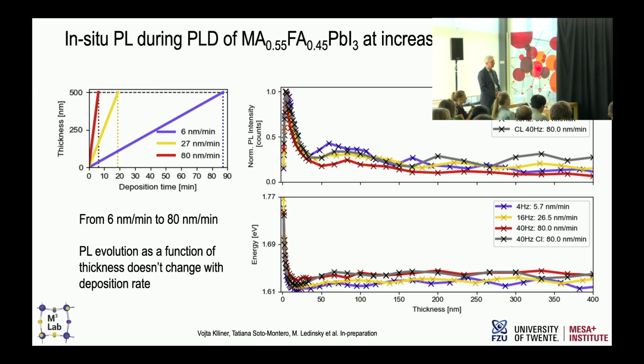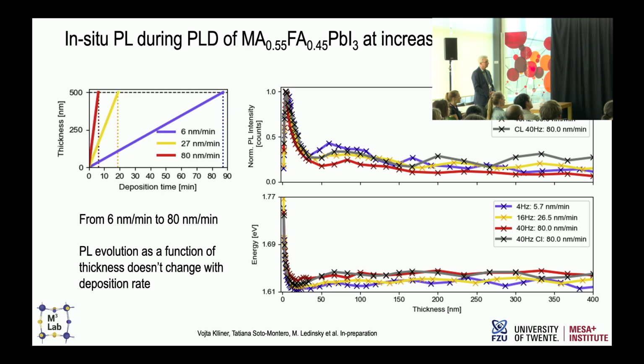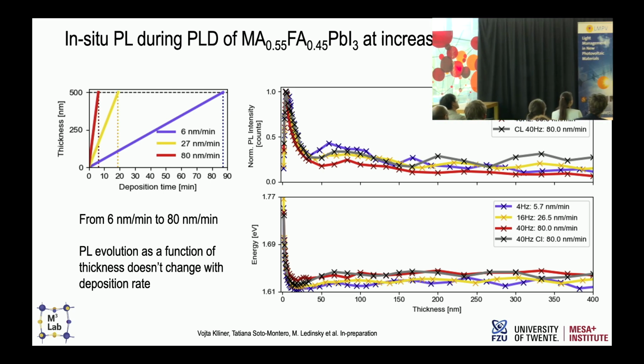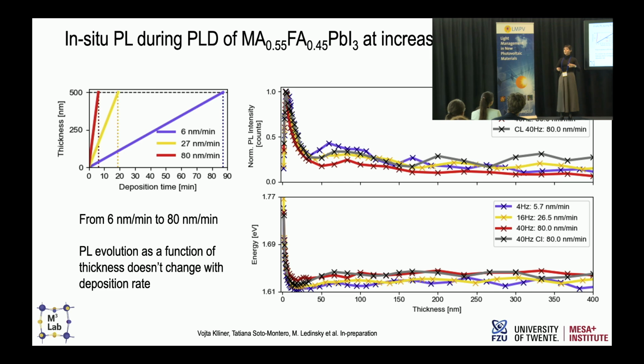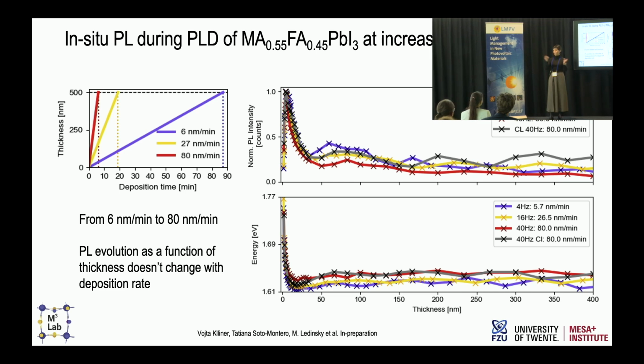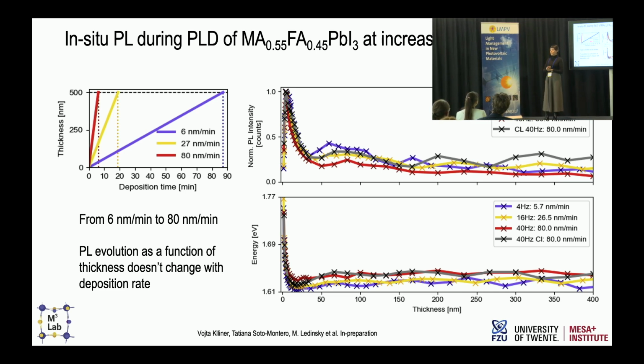Yeah, so that's also different because it's a little bit more confined. At least the inorganic part is much more confined. The organics do extend a bit more in the chamber. But we are still trying to demonstrate that. Our hypothesis is, for sure, it's not covering everything. I mean, you have to do many, many depositions. In this way it's different because evaporation is a big cone like this, right? In our case, it's like this. And that's why we actually need to scan the substrate to cover everything, because you don't cover a very large area with just one steady position.